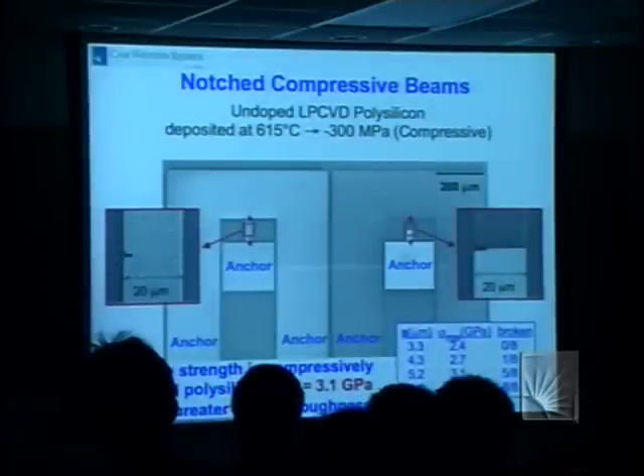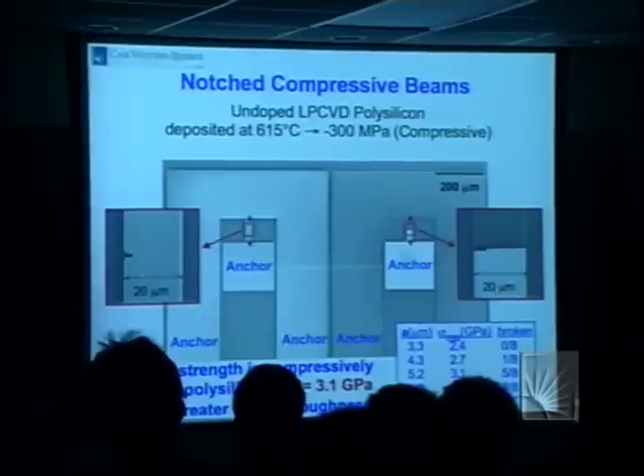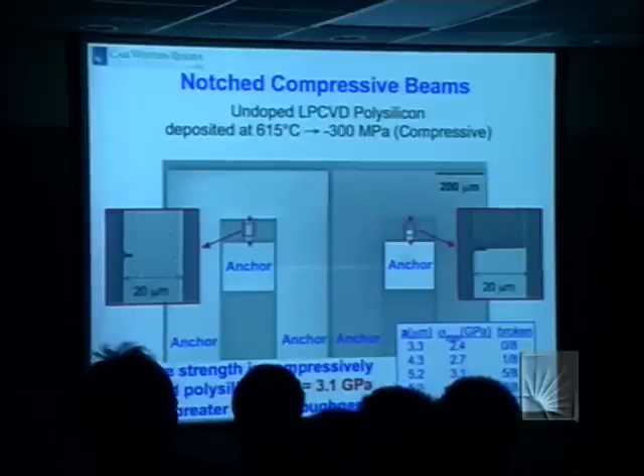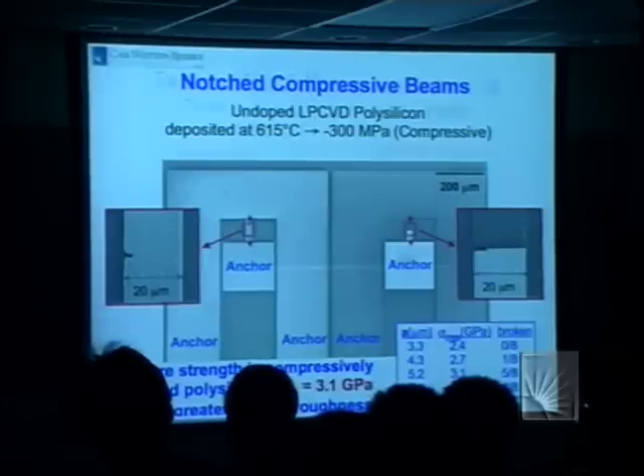And here are our examples. It's anchored here at this notch depth. This is 300 megapascals compression. At this notch depth, the tensile strength of the film was not exceeded, no failure. Here, the failure did occur. This is our statistics. The strength is a little less than in compression, and the reason is because, you remember, well, I'll just show you, you don't have to remember.